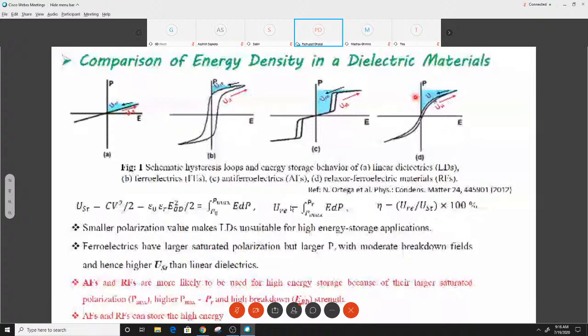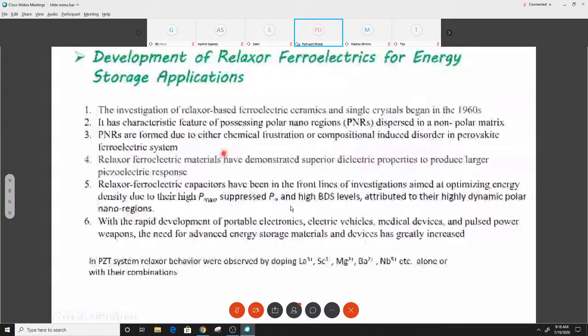So the linear dielectric and ferroelectric have moderate energy storage capacity, but antiferroelectric and relaxor ferroelectric can be suitable for high energy density capacitors. Relaxor-based ferroelectric materials began to be studied in 1960, and they have the feature of possessing polar nanoregions dispersed in a non-polar matrix. And polar nanoregions are formed due to chemical frustration or composition-induced disorder in the perovskite ferroelectric system.